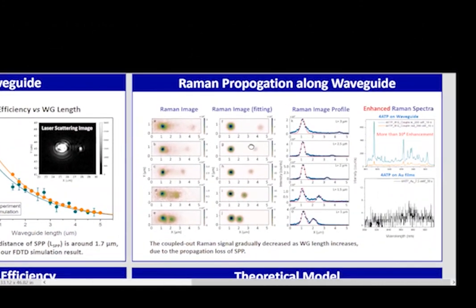And then we show those structures can also be used to control the Raman scattering of the molecules which were bonded to the waveguide. Importantly, we show more than 10^4 times Raman enhancement can be achieved compared to the molecules which were bonded just to the surface of a gold film.